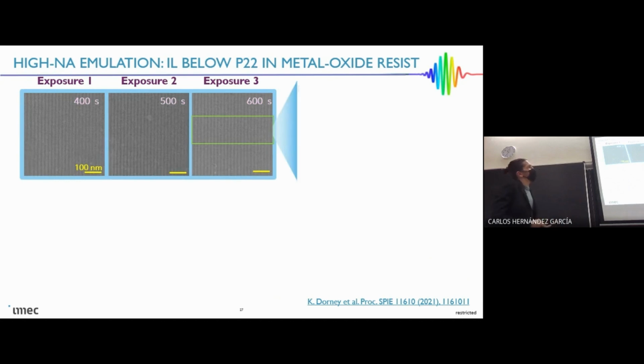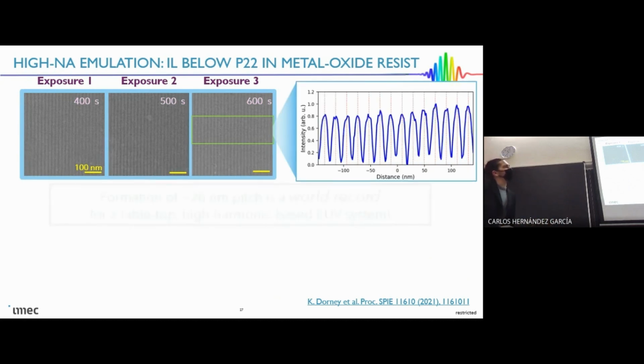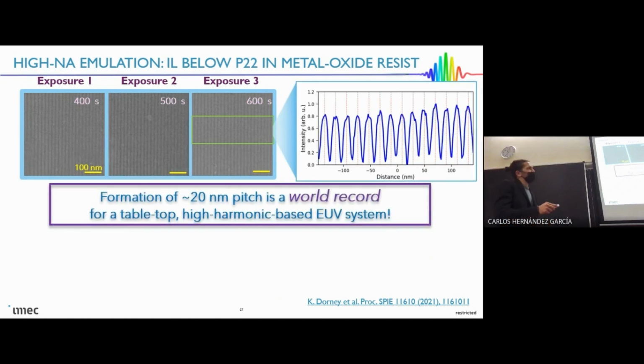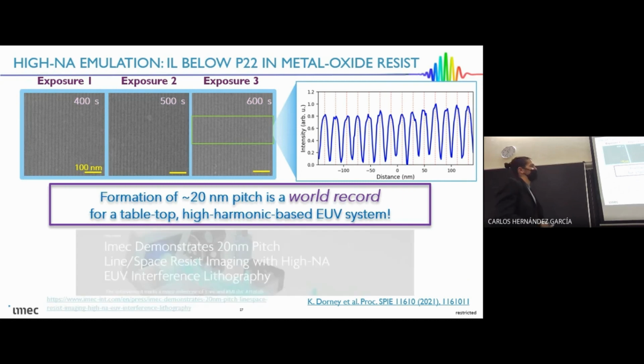But if we take an integrated line out of here, we see that we actually formed a pitch, or a wavelength, of this grating that's on the order of 20 nanometers. Now that number might not sound like much, but it's actually a world record for this sort of tabletop system, and is a value that they can't actually do in those EUV scanners. We were quite excited about this because it showed that EUV light, especially from high harmonic generation, has the capability to actually do lithography. We can use this to study the lithographic process.